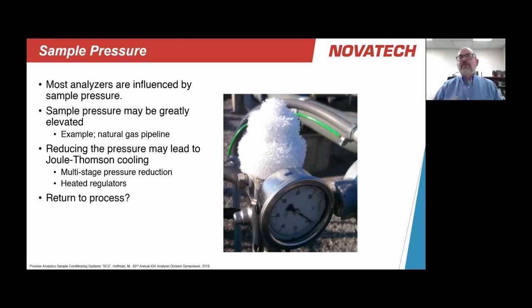Sample pressure. We talked about pipelines earlier. If a pipeline is operating at a relatively high pressure, me bringing the sample out of that and into an analyzer that is designed to operate at near atmospheric pressure presents a challenge. I have to be able to reduce the pressure in a controlled way and not lead to problems like Joule-Thomson cooling and freezing up my regulators, things of that nature. The other issue that I have to think about is if I have to now return the unmeasured sample or the unaltered sample back to the process, how am I going to do that? I either have to find a low pressure point within the plant, or I have to have the ability to bring the pressure back up again to be able to re-inject it into the process.